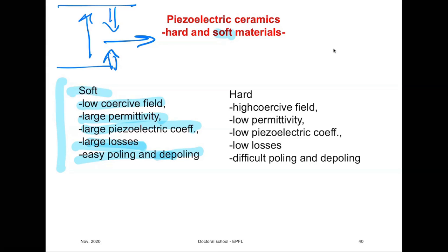On the other hand, hard materials have in general a high coercive field, although this is a statement that is, as you will see later, not really accurate. They need very large fields to open up the loops, but once opened up, you will see that they have the same coercive field as a soft one. So this is a statement that should be taken with a reserve.